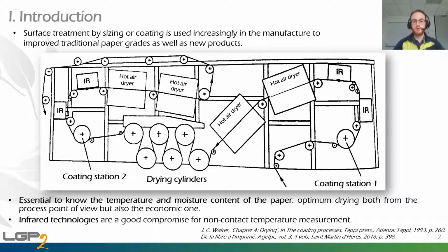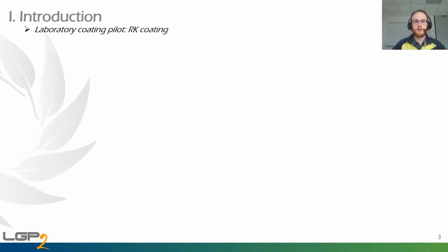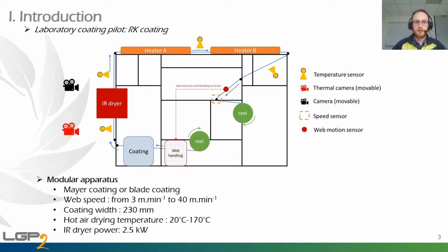In order to have information concerning the temperatures, infrared technologies are a good compromise for non-contact temperature measurement. And this technology is used on our laboratory coating pilot from RK Coating. This pilot is a modular apparatus with different technologies for coating station, as a Mayer coating or blade coating. We have also control on the web speeds, but the coating width is fixed. We have here two hot air dryers, which the temperatures could be fixed between 20 and 170 Celsius degrees, and an infrared dryer with a power of 2.5 kilowatts.